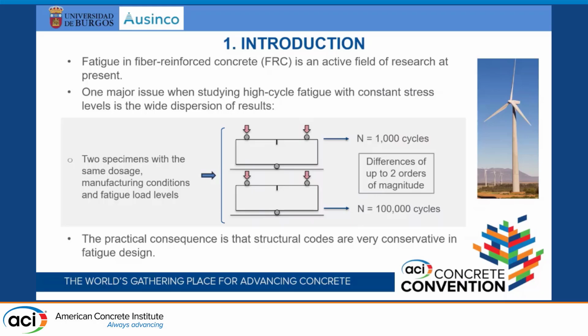However, there is a major issue when doing research in fatigue of fiber-reinforced concrete, FRC, and this is the high scatter of results that we find, particularly when we subject specimens to high cycle fatigue between the same load levels. This is just an example: if we have two equal specimens with the same dosages and subjected to the same load levels, we can find dispersion of about 2 orders of magnitude, for example, between 1,000 cycles and 100,000 cycles. Same dosage, same load levels.